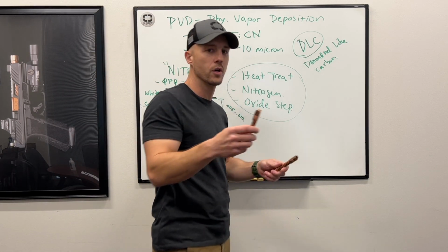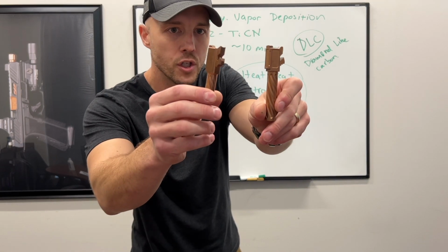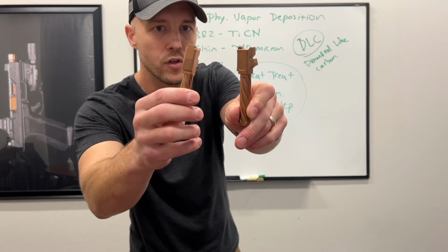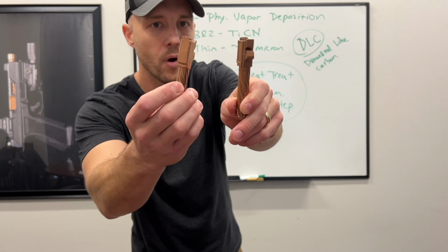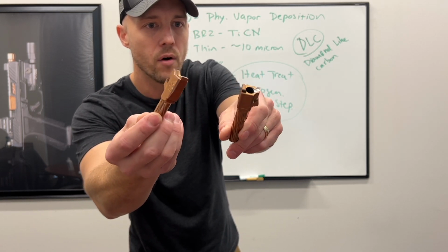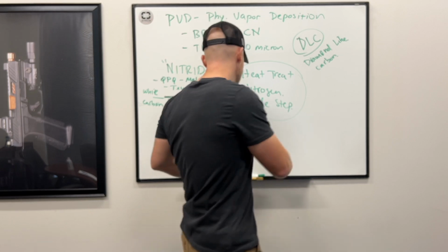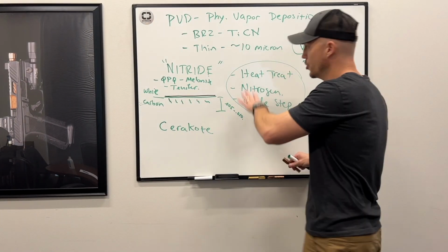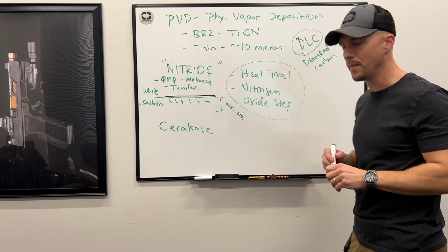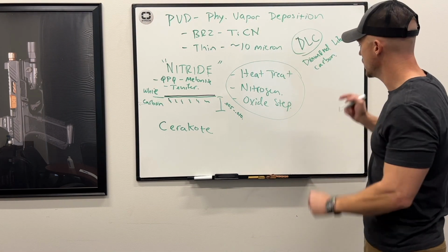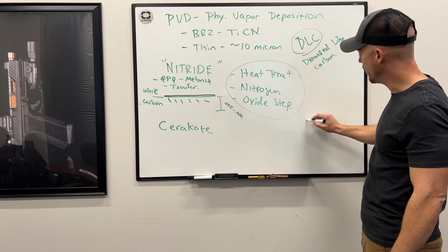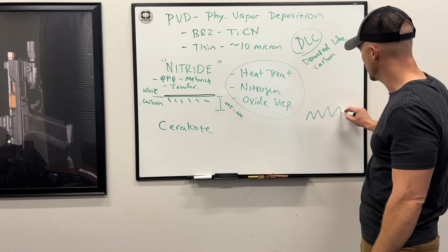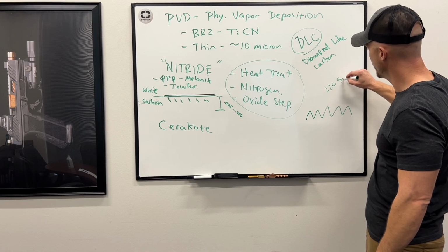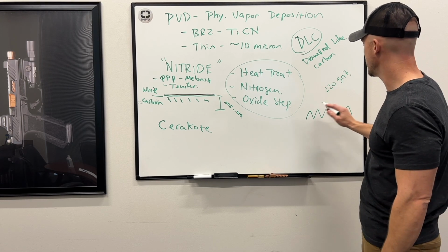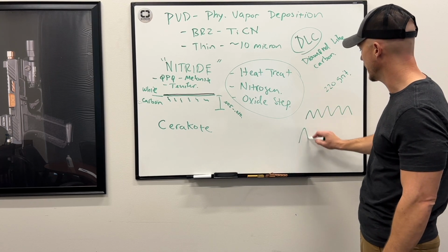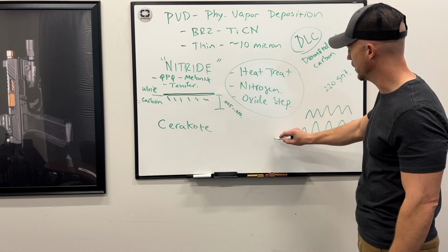So this is an older generation bronze barrel. This is a newer generation bronze barrel, okay? So you can see we've changed that pre-coating process, and the new one is much shinier, right? So what does that mean? Well, it means it does better with wear. And it's kind of true on any part. The better the polish is, usually the better it wears, especially with PVDs. Why? Well, if at the microscopic level my surface is like this, let's just say I use 220 grit aluminum oxide. Okay, that's going to be less rough than, let's say, a 100 grit or something like that.